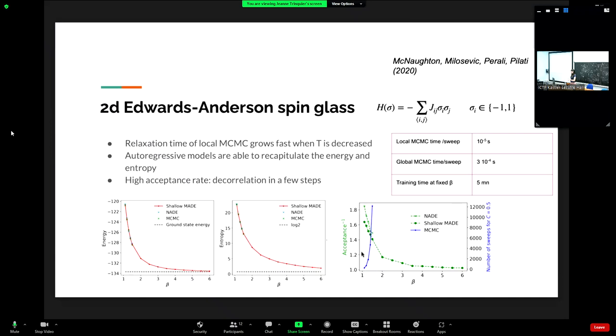And so we applied this simulated tempering procedure. We start at T equal 1, and we slightly decrease the temperature. To check that the model was a good model, we checked that we were able to reproduce the energy and the entropy of the true model. You see the equilibrium results are in green. Of course, after a certain time we cannot compare with the true value because we cannot do local MCMC, but we also found that we were able to reach the ground state.